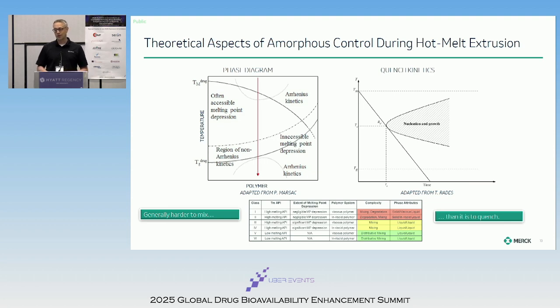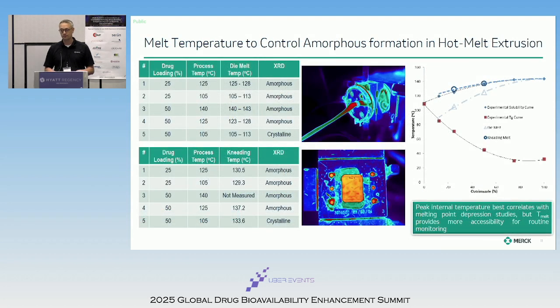Although less frequently seen, depending on the quench kinetics, you can actually potentially drive to a state where you would see recrystallization occurring during the cooling event. I think in all the years that I've been doing melt extrusion and all the products that I've seen across the different companies, I've only encountered this one time. It is very visually cool to see as the extrudate comes out and then recrystallizes, but not frequently encountered as a failure mode in amorphous dispersion products based on my experience.